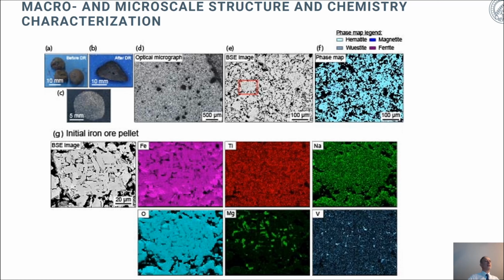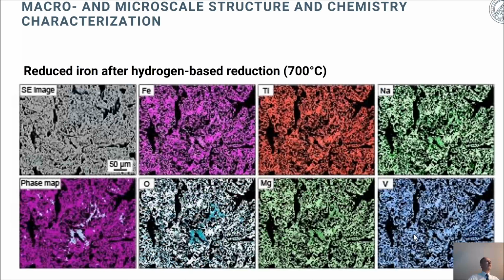Because depending on where you get these ores from, you also have chemical heterogeneity in the material and not only structural heterogeneity. This is shown here from a micrograph in a BSE image of the initial iron ore pellet, and you see in terms of the iron distribution that you also have other elements such as titanium, sodium, even vanadium, magnesium, and so on. So that means you will later see, when we go to a near atomic scale analysis, that these features also play a role in the reduction kinetics.